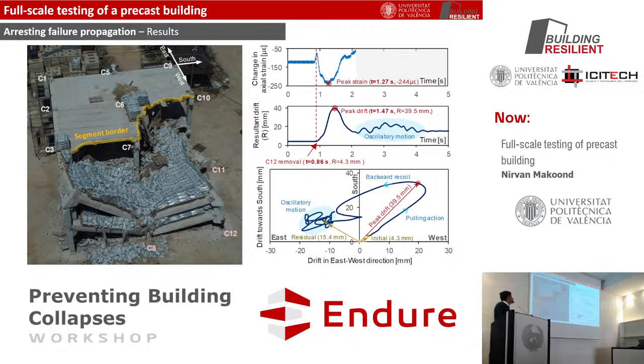And here, basically, these are some of the interesting results we were able to collect. So as we can see, only the influence area of the initial part collapsed, and basically here the connections failed, and along all the slab there was debonding of the reinforcement. In these plots I'm showing the change in the axial strain for column C7 and drifts measured in the intact part of the structure.